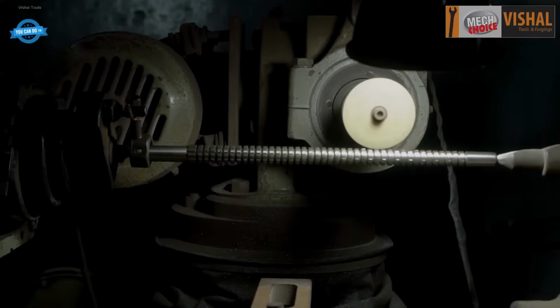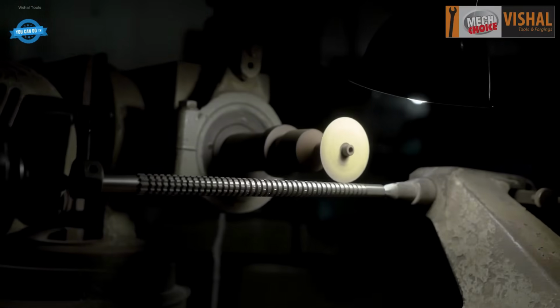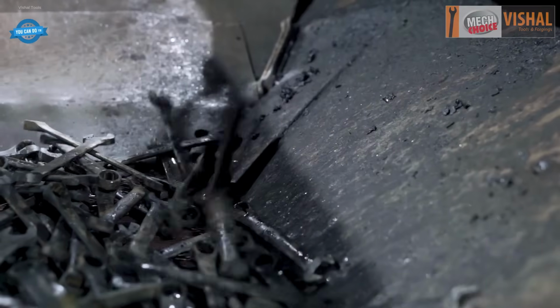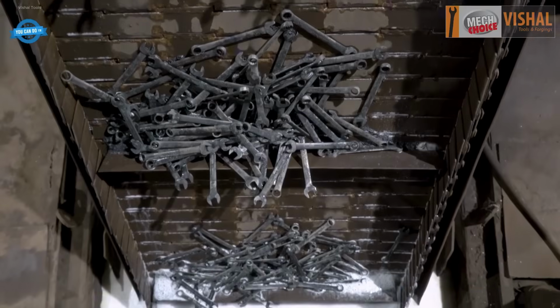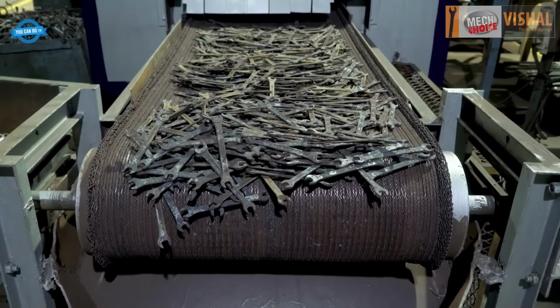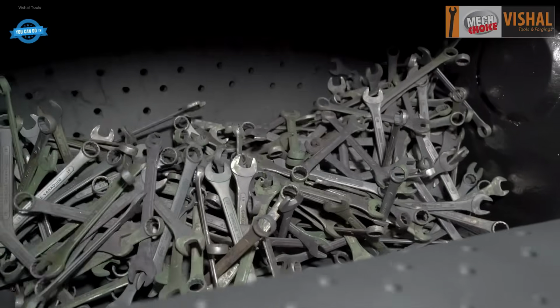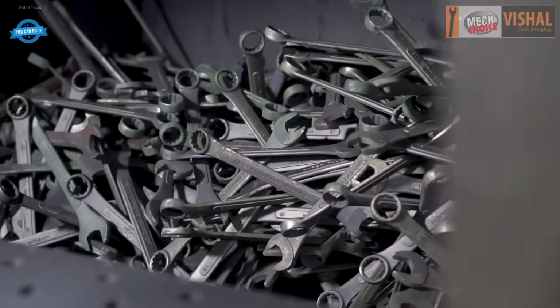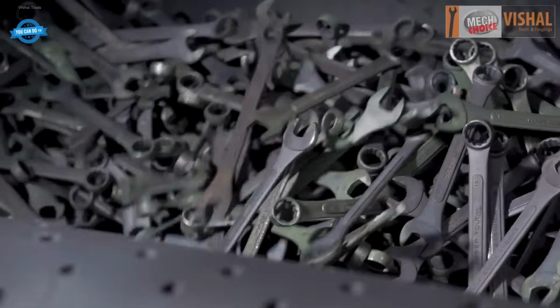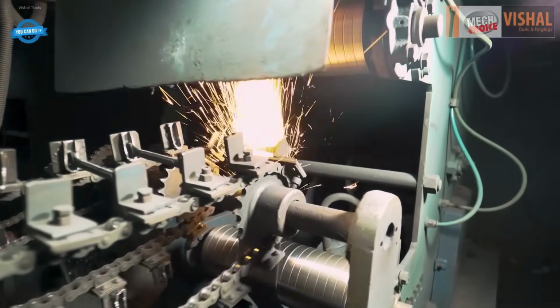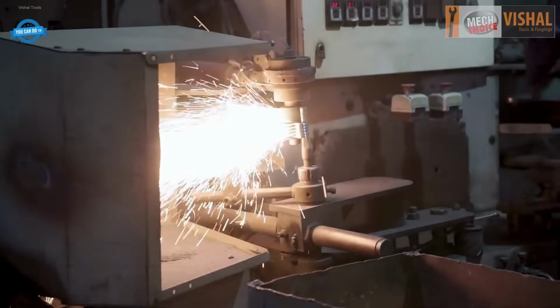In the machining phase, broaching shapes the wrench's jaws with tolerances of 10 to 20 microns. Broaches are made in-house, ground, and tested using micrometers and plug gauges. Next is heat treatment, where wrenches are hardened, quenched, and tempered in an electric furnace. Each batch is hardness tested, followed by a torque test to verify mechanical strength.